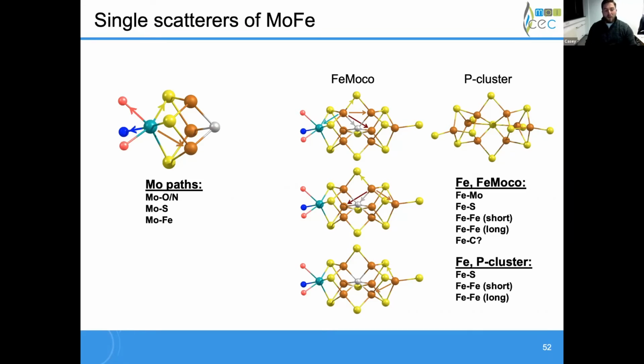And so from the molybdenum standpoint, it's really simple. We have oxygen and nitrogen as relatively light atom scatterers. We have molybdenum-sulfur, and we have molybdenum-iron. Depending on your resolution and what you believe from the crystal structure, maybe you can differentiate the oxygen and nitrogen, but I'll touch on that later.